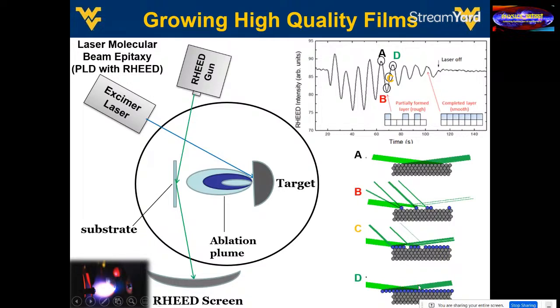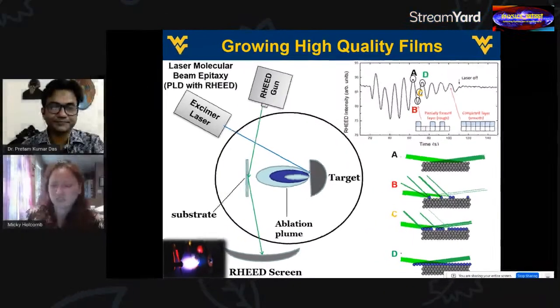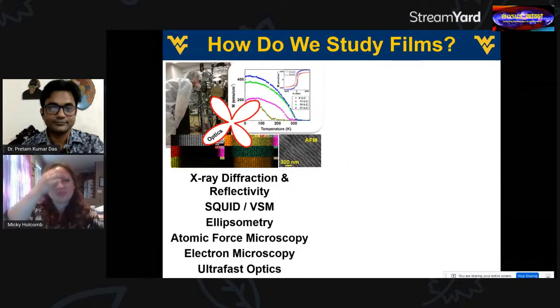And so you get these nice oscillations that you can observe and actually monitor your growth one layer at a time. It's not trivial to do, but it's doable, and it allows you to actually grow oxides with better precision than you can with molecular beam epitaxy. There may be people that would argue with me about that, but we can discuss it if anyone wants to. So it's a very nice technique for growing films.